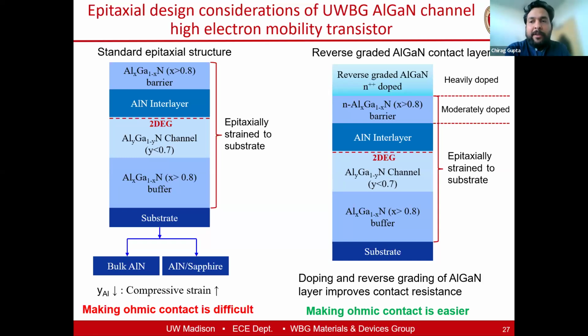However, the challenge is these are wide bandgap materials, and unfortunately, the metals that we have, their work functions are very limited to the metals that are available to us. So making ohmic contact, which is not that challenging in gallium nitride, at least now, is still extremely challenging in these ultra wide bandgap materials. So ohmic contact, we don't think about it too much when we are thinking of on resistance breakdown voltage, but in these ultra wide bandgap, it's something that cannot be taken lightly.